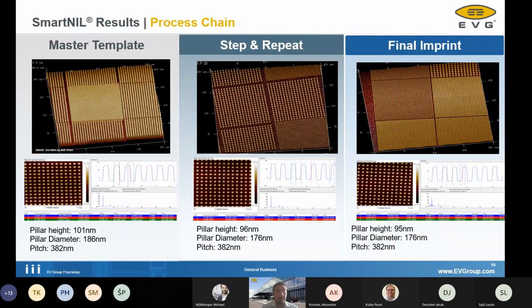And you can see we can keep the pillar height and the pillar diameter almost constant. There are some deviations due to shrinkage of the materials. That's quite normal for all UV curing material. However, if you understand this whole process, you can bias this and then compensate already in the master design. This was done, the whole project, and now they have a very nice product that's going to the market.